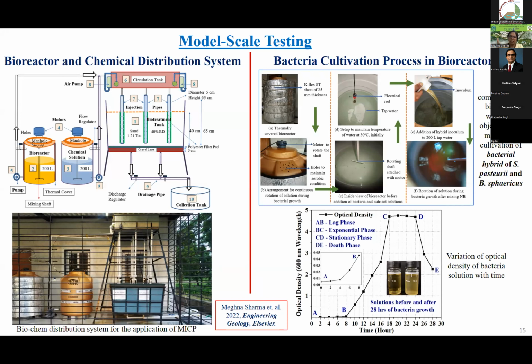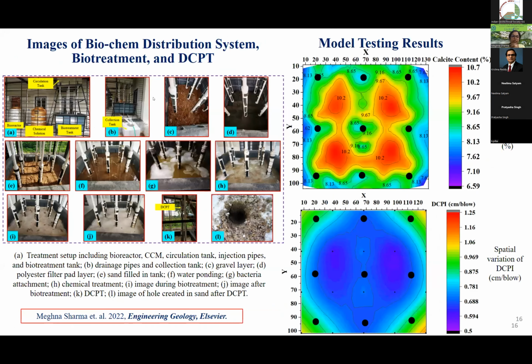At an optical density of 2, this solution was provided into the biotreatment tank. In the tank, initially a gravel layer was placed, then a polyester filter layer, and sand was filled. To expel the air voids, water was provided, and then the water was drained out. This is bioaugmentation, and bacteria need to be attached to the soil for 24 hours. The bacteria solution was provided into that tank.